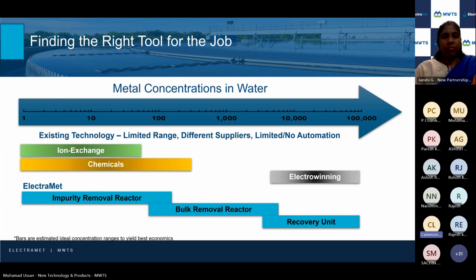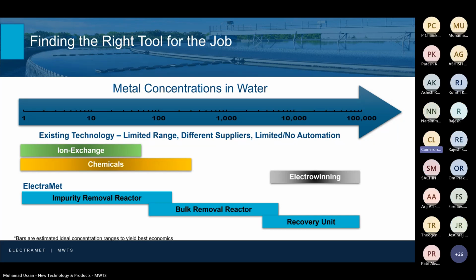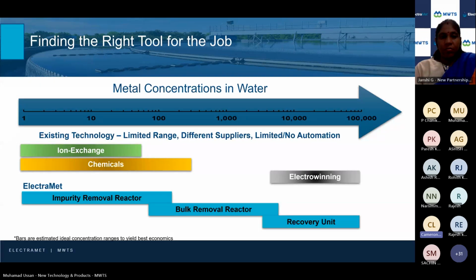And that is why they tend to truck off that concentrate instead of processing it down to discharge compliance. Because either way, you have to do some ineffective, unsustainable, high-cost solution to cover that gap. And ElectraMet has solved this problem by using electrochemistry and developing a series of reactors that can process the entire concentration range in a single skid. So whether you're starting in the lower ppms that you see in CMP, or at the high concentrations that you see in the wet etch processing, our solutions can process it all the way down to environmental compliance and discharge regulations, while also recovering that copper as a value add and not sending waste to landfill.